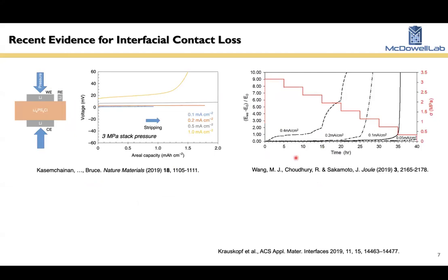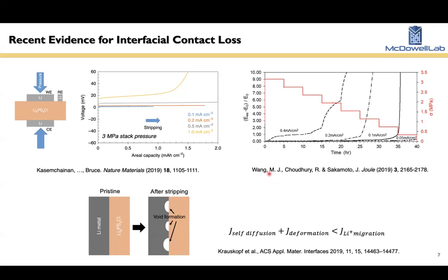A few years ago now, we focused on investigations of contact loss in these materials. It's a void formation and contact loss at the interface between lithium and a solid electrolyte. And we did some visualization of this, which I'll show you in a second. But this was inspired by some really key electrochemical observations by a number of different groups 4 or 5 years ago now.